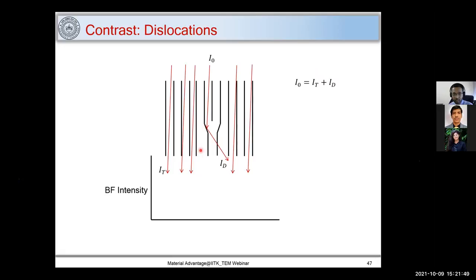If you look carefully here, you can see that I have more transmitted intensity compared to this part, because in this part diffraction is occurring. So I get a dip in intensity, and that creates a contrast. That is how we can see a dislocation, because of the diffraction occurring near the core of the dislocation, since this region will satisfy Bragg's condition. So this is called diffraction contrast.